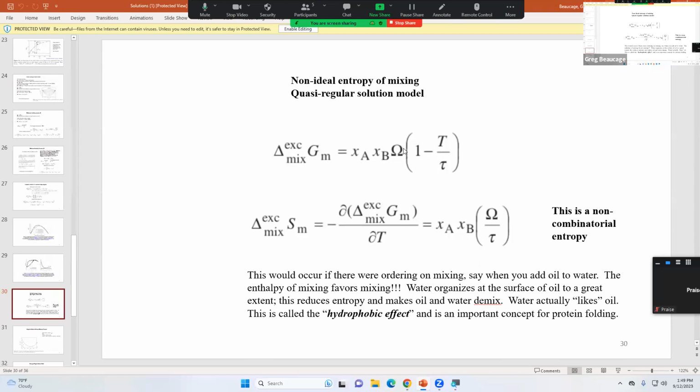It's a weird thing. If you have some polymer like Post-it glue, sticky, and you try to wipe it up with hot water, it doesn't wipe up. But if you wipe it up with cold water, it just wipes up. So it's the opposite of what you think. Cold water dissolves it. Basically all polymers mix this way because there's no entropy of mixing. The only way they would mix is if you had an enthalpic interaction that made them mix. Almost all polymer mixtures are like that. Some other systems, like biological systems, have that same behavior. They wouldn't normally mix, they only mix because of an enthalpic interaction.